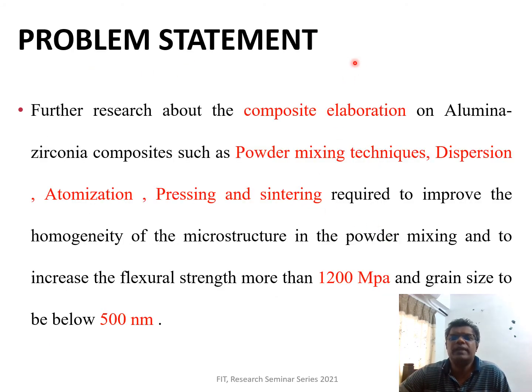So the problem statement for my research is that further research is required for the composite elaboration of alumina zirconia in terms of powder mixing technique, in terms of dispersion, how well the zirconia has been dispersed on the alumina surface, and atomization, pressing and sintering, required to improve homogeneity of the microstructure in powder mixing, to increase the flexural strength up to 1200 megapascal and grain size below 500 nanometer.